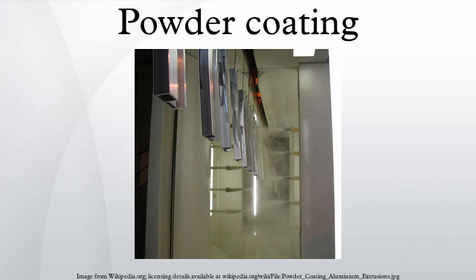Another method of applying powder coating, called the fluidized bed method, is by heating the substrate and then dipping it into an aerated, powder-filled bed. The powder sticks and melts to the hot object. Further heating is usually required to finish curing the coating. This method is generally used when the desired thickness of coating is to exceed 300 micrometers. This is how most dishwasher racks are coated.